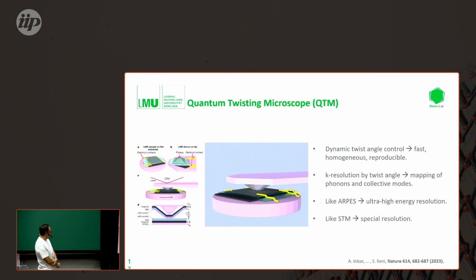When this technique came along, the quantum twisting microscope, which was first introduced by Shahal Ilani about 2 years ago now, I found this a really interesting way forward, because this technique would allow us to study the larger phase space of these materials and obtain phase diagrams which are twist angle dependent at the same time.